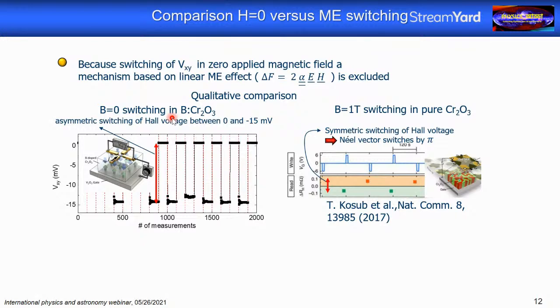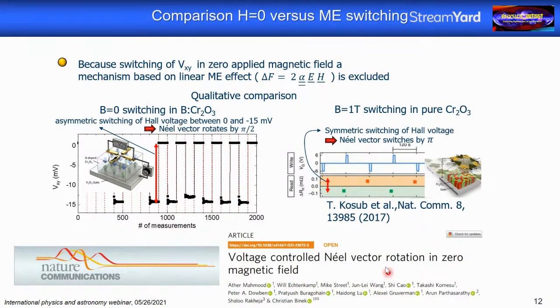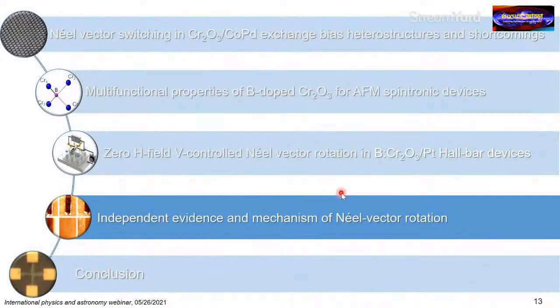We do not need the magnetic field that is breaking the time inversion because we do not switch by 180 degree, we switch by 90 degree. But for the applications, that is a perfectly fine contrast, which we can of course use in devices, memory or logic. Okay, and that is a recent publication here in Nature Communications where we published this result. So we think that's a big deal because we can do that also up to 400 Kelvin.